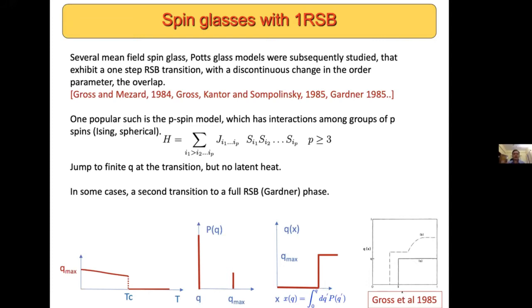And there are several models, as I already mentioned, but one popular such model is the so-called p-spin model, which has interactions among groups of p spins. So each term in the interaction Hamiltonian involves the state of p spins and a corresponding strength of interaction, which is a quenched random variable. And for p greater than or equal to 3, the nature of the transition changes as compared to p equal to 2. There's a jump in Q at the transition, but no latent heat. This is schematically shown at the bottom of the slide.